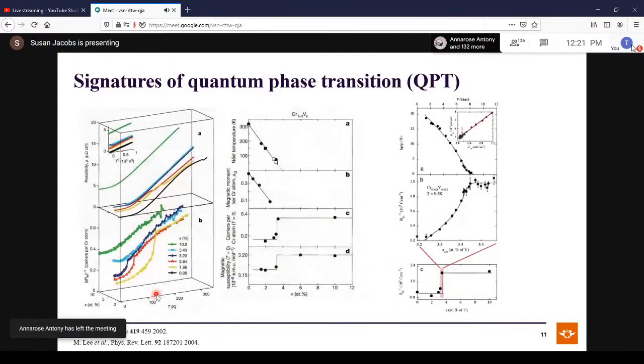Okay, so how do we know if we have a quantum phase transition? We have certain signatures associated with it. We can see the number of carriers drops as you go into the ordered state, as well as the magnetic susceptibility. This is because of the reduction in the density of states at the Fermi level. Here we have chromium vanadium bulk alloys. The resistivity, on the other hand, transitions smoothly through the quantum critical point. But if you look at the low temperature dependence of resistivity on the cube of temperature, you see that the dependence is independent of the dopant concentration. So it's all straight line dependence. This was for bulk chromium vanadium alloys, and the tuning parameter here was doping with vanadium.